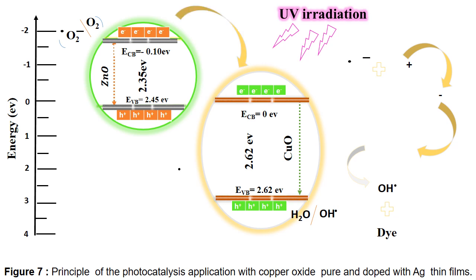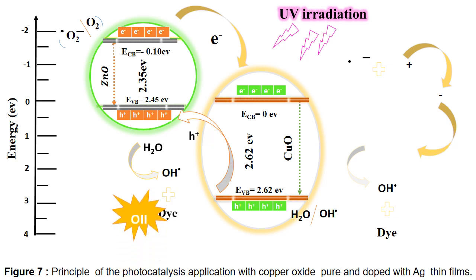Principle of photocatalysis application. The hole in the valence band interacts with water to produce hydroxyl radicals, and the electron in the conduction band interacts with oxygen to produce superoxide radicals. The superoxide radical interacts with hydrogen cations to produce hydrogen peroxide. Each hydrogen peroxide interacts with a photon to produce two hydroxyl radicals. The hydroxyl radicals interact with the dye and degrade it, producing water and carbon dioxide.